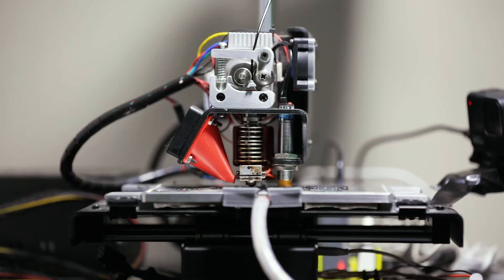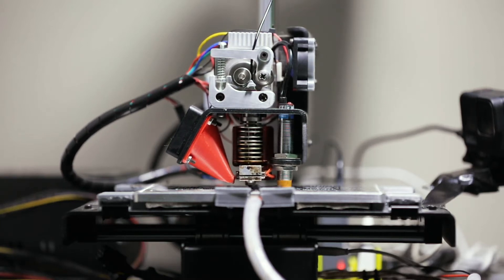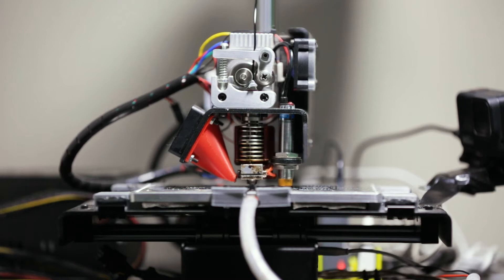The PLA version I flew on the drone — Mark 0.5 — I broke it on the first flight, but I was able to put a GoPro on and make sure it was going to work. Then we went to NinjaFlex, and yeah, big difference. Not even in the same realm — it can take hits, and I hit the ground a lot. It's much more difficult to print though. You have to print very slowly because the flexible material can wind up and jam the extruder, causing clogs.